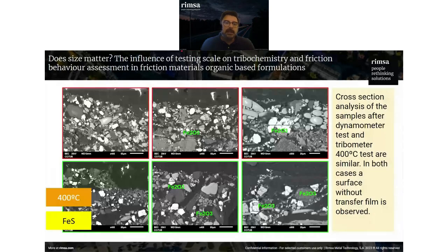If we analyze the cross section with SEM, in the region nearby the working surface, you see that all the iron-containing particles give the signal of iron oxide. So we are able to replicate this oxidation in the same way in the dynamometer and the tribometer.